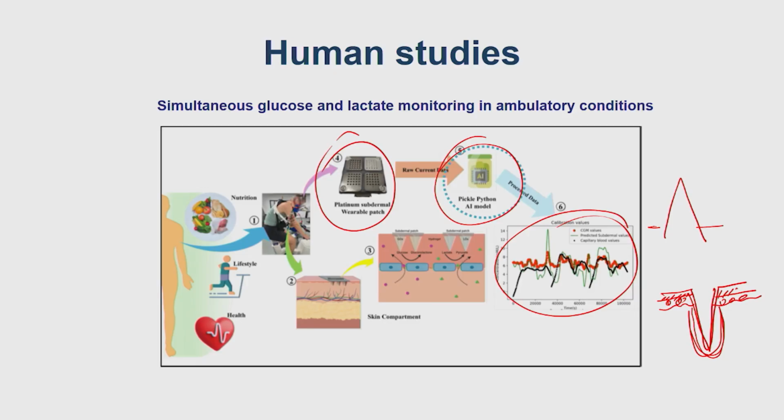But sir, if that's a porous material, then the contamination chances are high, right? If the needle is made up of porous materials. Yes, if the needle is made up of porous material, but don't forget, I'm talking about solid microneedles. If the needle is covered with a layer of metal and then functionalized, and on top of that you have a polyphenol layer, then there's nothing that can actually ooze out through the needles or into the needles, right? And we are sitting in the subdermal space and doing measurements there.